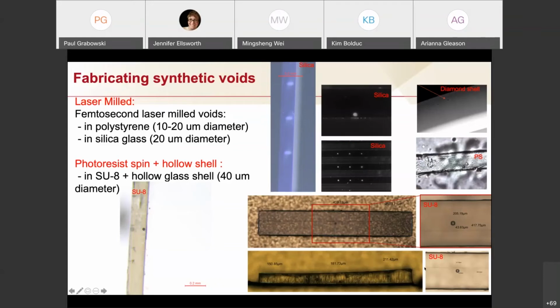We've also pursued another fabrication method. We're not actually using a polystyrene, but rather a photoresist plastic, essentially a polymer, called SU8, which is used in the semiconductor industry for different nanofabrication tools. But here the SU8 is our plastic, our material of interest, taking the place of polystyrene. And in it, I can place quite specifically a void. But this void is technically a hollow glass shell, and the wall thickness is a micron or less. So we include that in our rad hydro simulations, that it does have this wall thickness, but we are hoping this is a good starting place for mimicking a void in a plastic.